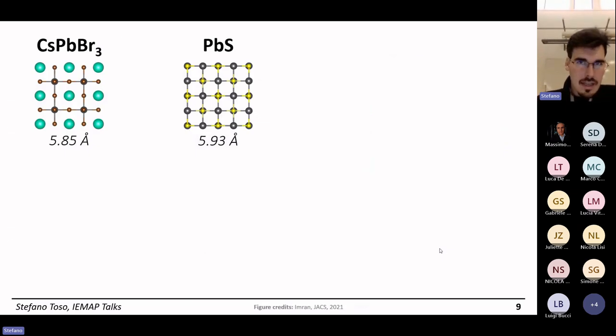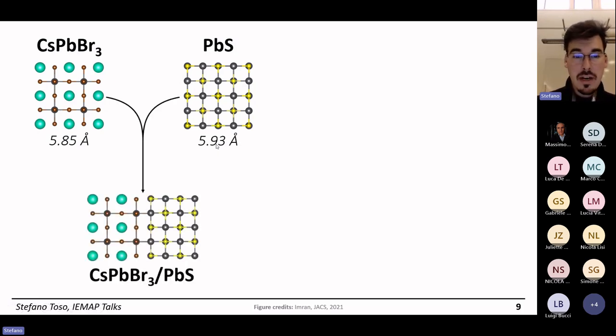So here is a realistic example that came up in our group a few years ago, where we were targeting an interface and we ended up having this kind of issues. The interface that we wanted was between two semiconductors, cesium lead bromide, wide gap, but like visible range semiconductor direct gap, and lead sulfide, the typical infrared semiconductor, right? If you have a look, the structures are different, but they are reasonably similar. Both materials are cubic, they both contain lead, the lattice constants are quite comparable. So what we were trying to do was to do an heterostructure between these two materials, right?